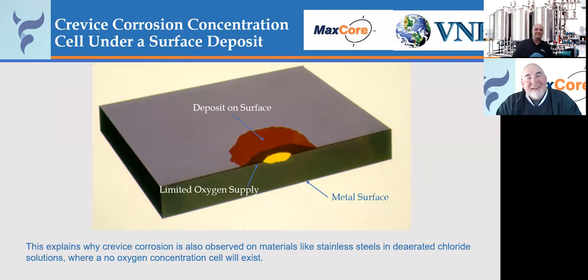Another crevice that can take place that we a lot of times don't think about is actually product debris on the surface of the steel itself. This is an artificial crevice that is formed just by surface deposits on the surface of the steel. So what typically happens in this type of place, when you have product buildup on the surface, you basically limit the oxygen supply underneath that debris. And you still have those areas of high chlorides that are trapped underneath that debris with the product itself.